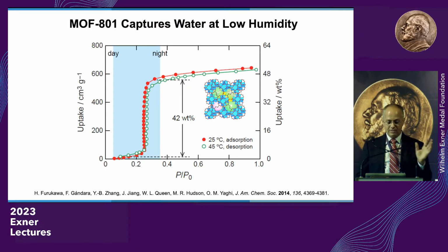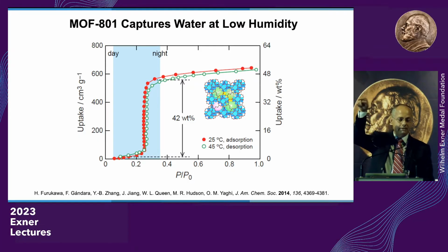Okay, that's very low humidity. That's typically what the humidity is in most deserts most of the year, or desert regions, I should say. And I think the other amazing thing about this material is that it takes up the water in a cooperative fashion. There's a very sharp uptake behavior, which tells me there's some cooperativity in the way the water is going into the pores. And the third amazing thing is that you can take out the water, in green here, at 45 degrees C.